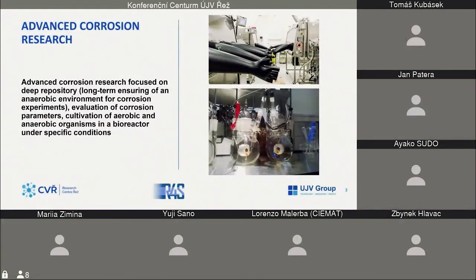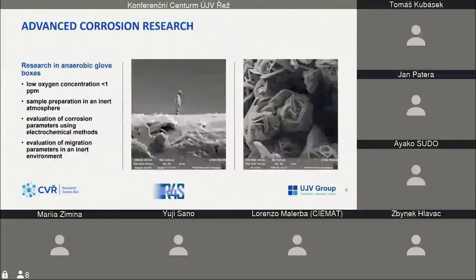The first part focused on the deep repository research is our advanced corrosion research. We specialized in long-term ensuring of an anaerobic environment for corrosion experiments, evaluating corrosion parameters, and cultivation of aerobic and anaerobic organisms in a bioreactor under specific conditions. For this purpose, we have 4 anaerobic glove boxes, which are able to reach very low oxygen concentration under 1 ppm.